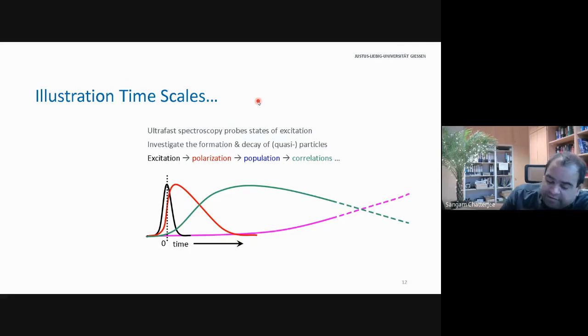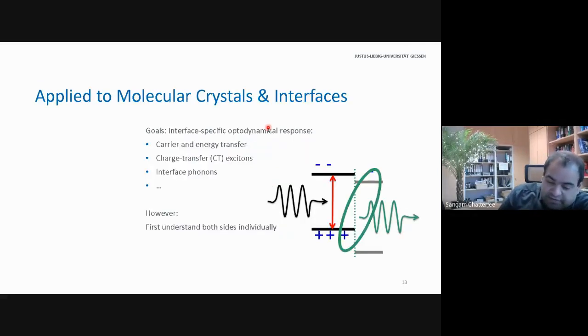So these scattering mechanisms can be very, very fast, so fast that you actually don't notice them, because they're faster than a cycle of light. But I hope to show you that in very well-ordered systems, these scattering mechanisms can be very, very slow, in particular if phonon interaction can be tricked. And a lot of physics actually happens in this polarization regime before you get a population of sorts which can relax, which can cool, and actual correlations will develop. Now, this concept can be applied to molecular crystals and interfaces. I've stayed in the PowerPoint physics regime, and I hope to illustrate here what an exciton and what a charge transfer exciton is. The exciton will actually come a little bit later.